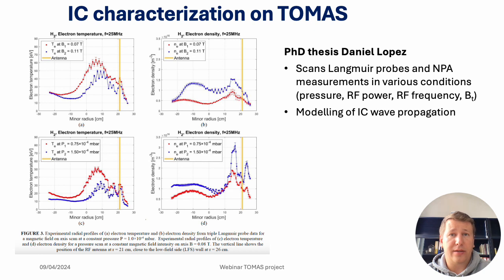To properly understand the dependence of the ion cyclotron wall conditioning plasma cleaning efficiency on the plasma parameters, we need to characterize the plasma. One of our PhD students did it. He studies the dependence of electron density and temperature, and energy distribution of ions and neutrals in ion cyclotron wall conditioning plasma with respect to neutral gas pressure, radio frequency power, frequency, and the magnetic field. These data are used to numerically model the RF wave absorption and propagation in plasma to optimize wall conditioning effects further.